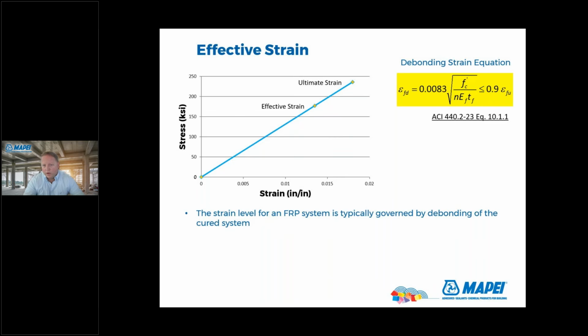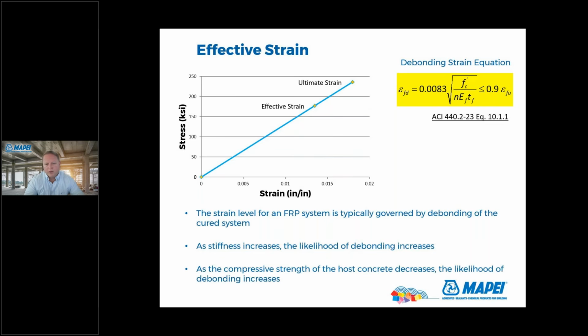If you look at this equation here, you can see that as the stiffness increases, the likelihood of debonding increases. So N is the number of layers on the bottom there, E sub F is the stiffness or the modulus of the FRP, and then T is the thickness of each layer. So the more layers that you're adding, this equation will eventually go to zero. And so at some point you're not really getting any additional benefit from a calculation perspective. You're just adding to the project cost. So typically around 4 or 5 layers is where this equation hits zero. Another thing is as the compressive strength of the concrete, the f'c, decreases, the likelihood of debonding increases. So that's why we have a minimum of 2,500. If you have higher strength concrete, that's just going to help you.